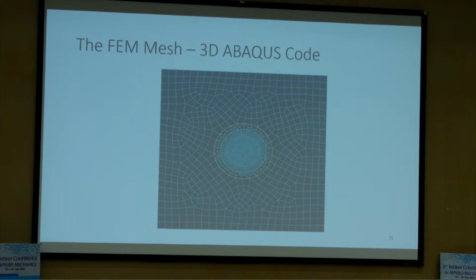This design is bad, really bad. We got a bad result, but later on we realized that this kind of expansion of mesh won't work. You really want to have an accurate, realistic result from this code. Equal, all elements are equal. It doesn't matter the elements away from the location of the projectile, everything is the same. The projectile and target aspect ratio of your element should be the same. You may end up with 2-3 million elements. One calculation will give you the right result. So right now we are doing about a 5 million element simulation for GRP with the delamination criterion, and we expect to get a very good result.